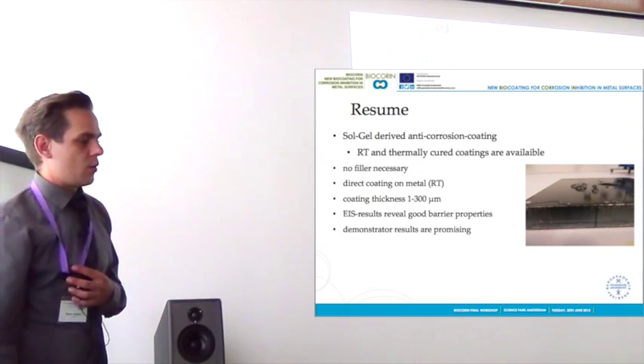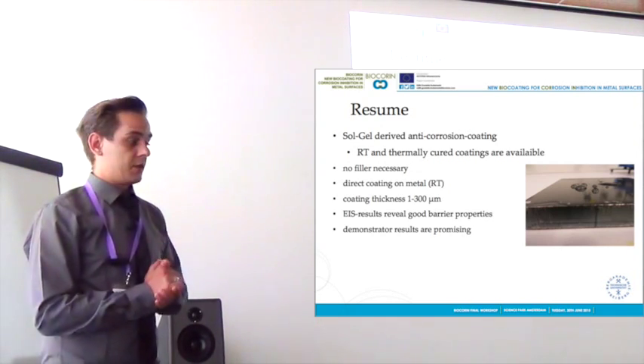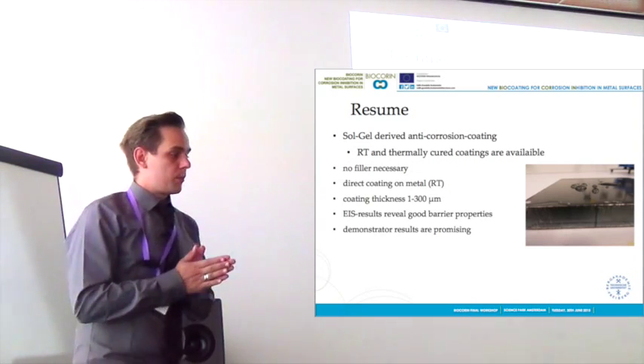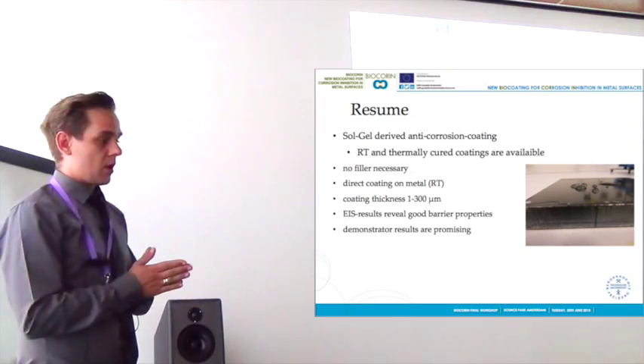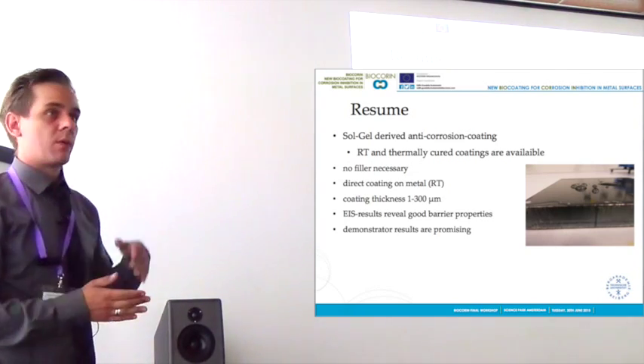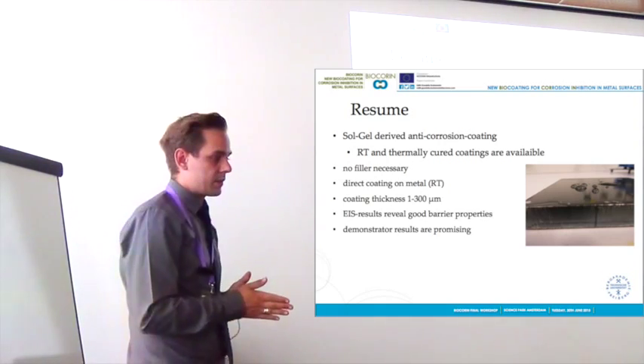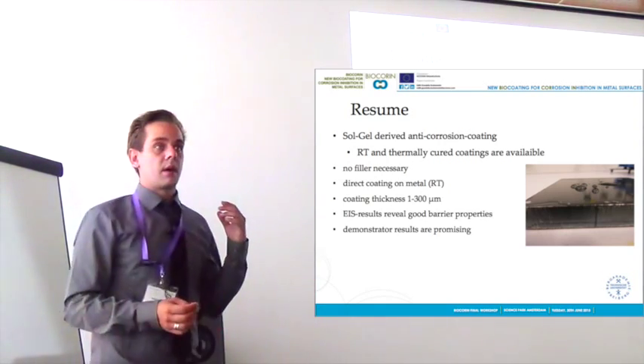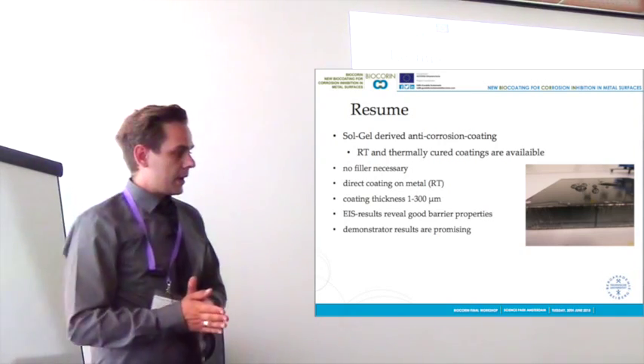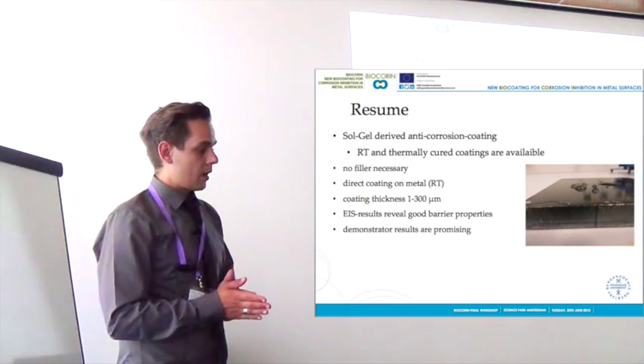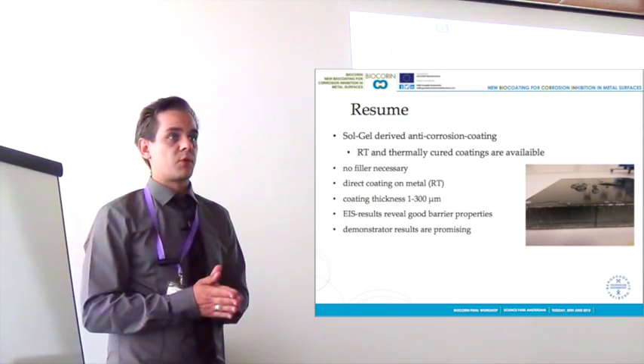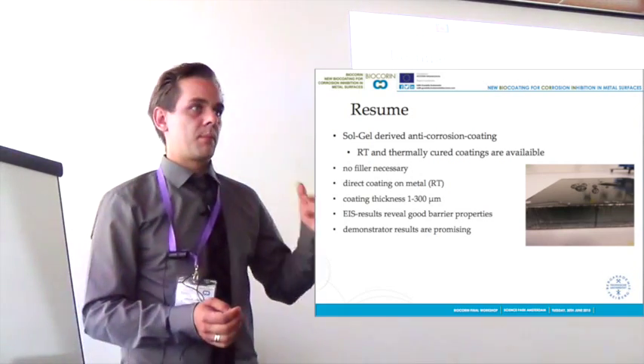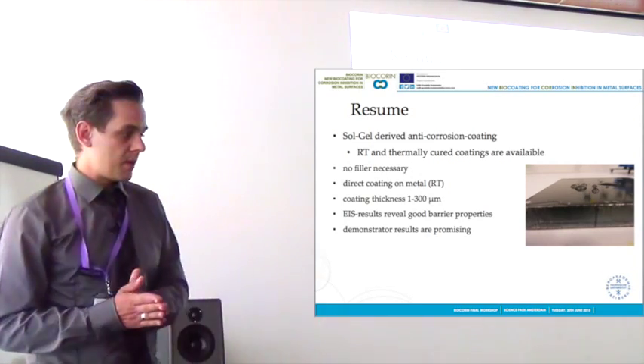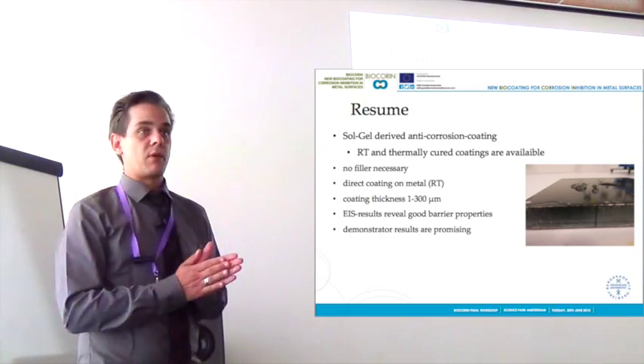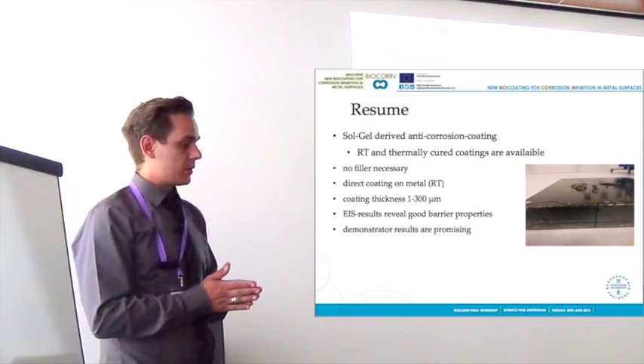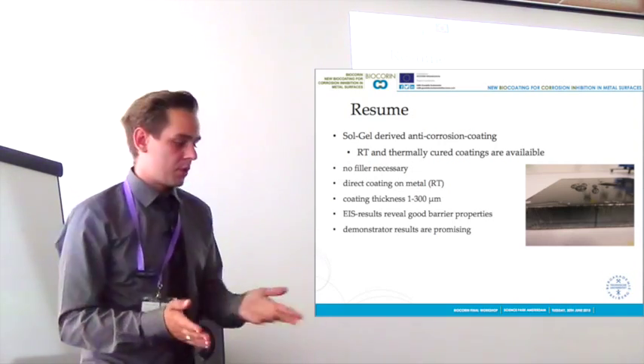So we can say we have developed a sol-gel derived anti-corrosion coating. We can cure it at RT or thermally. Both are working quite well, but B1 is the preferred system at the moment. No filler is necessary. That means it can be used as a clear coat, direct on metal. In the case of RT, the coating thickness can be from 1 micrometer up to 300 micrometers. The coating can be applied in different layers or just in one coating step. The EIS results revealed good barrier properties for both B1 and B2, and the demonstrator results are promising.